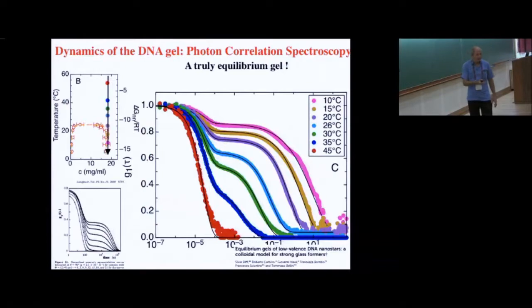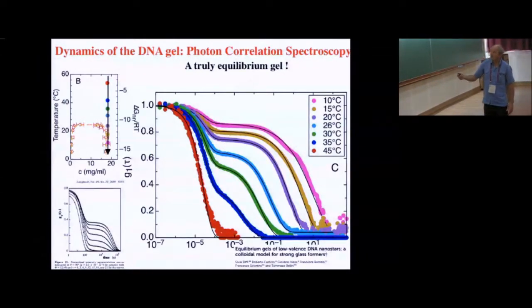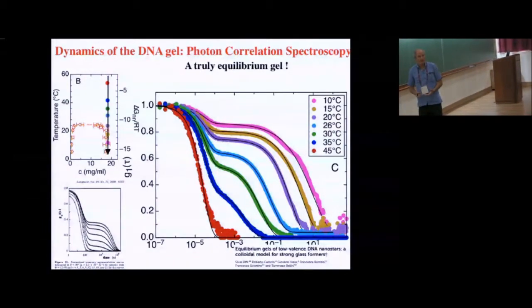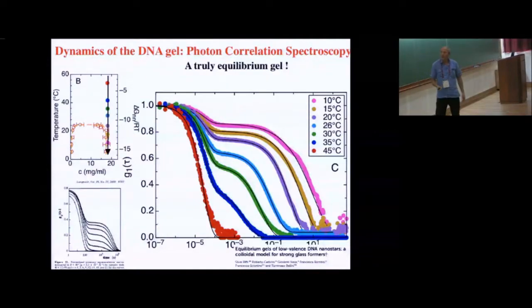Now we can look at these equilibrium gels. So now we can prepare our sample outside of the phase separation. We can go here, for example, to a density larger than the phase separation. And then we can measure with dynamic light scattering the density correlation function, the same correlation function that we've been discussing all this time. And this is the result that we see. I want to stress the difference with the glass phase. You see that there is a plateau, there is an alpha relaxation, exactly like in glasses. But you see that the plateau goes up and grows with cooling.